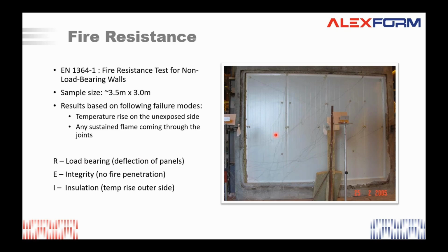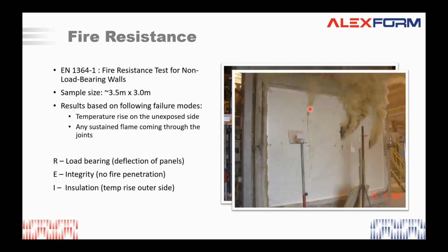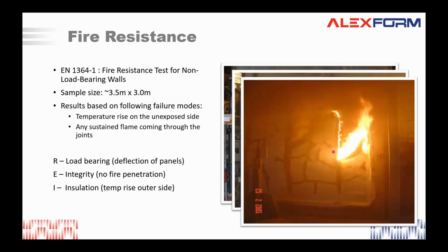So when the test is running, what you will see is that after some time, the smoke will start coming through the cracks because on the other side, the fire has already deformed the joint and started eating through your foam core, trying to reach the other side. And after a while, you see the flame coming through. And it's not like a short flame doesn't fail the test.